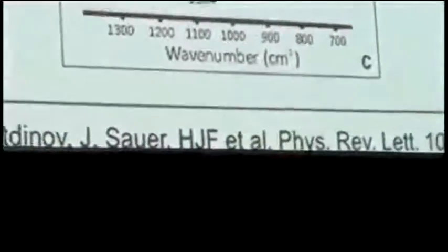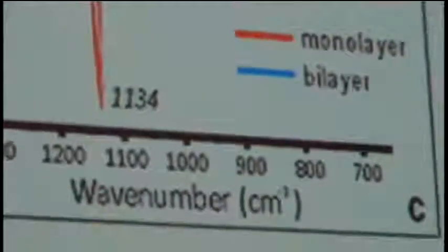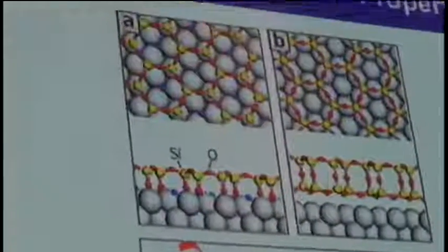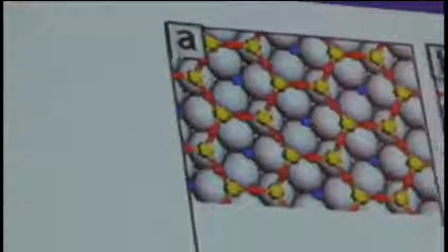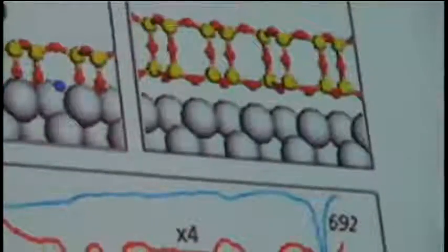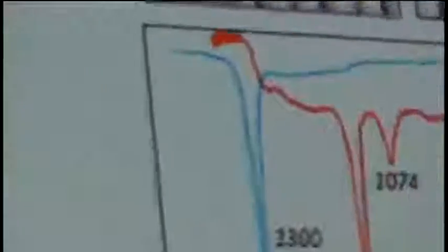What we have done is we have made silica films on ruthenium, on many other substrates. The interesting thing is usually a monolayer forms. Silicon, 4 oxygens around it. For a chemist, that's obvious. And one oxygen can bind to the metal, and that metal-oxygen bond is very strong, so you form a monolayer of that, very well ordered. You can find recipes where you actually flip that thing around and put another one on top, and you form this. The people who are very much into graphene, they call that silicatene.